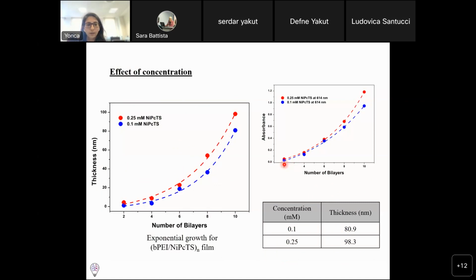So in the influence of concentration, let's increase the concentration by 2.5 times. And what I was expecting was a 2.5 increase in the thickness, but this is not the case. As you can see here, the initial overall film thickness was 80 nanometers, and in the increased concentration, it's around 100 nanometers. So why is it not really 2.5 folds? So we have an exponential growth.